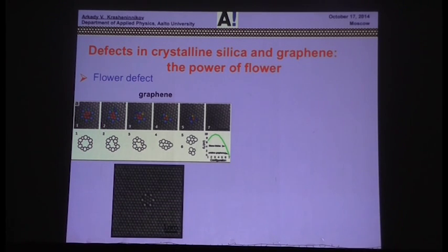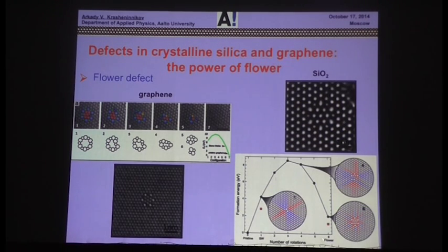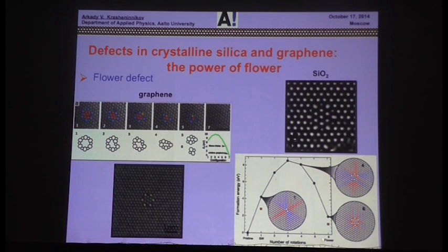Versus the beautiful flower defect in graphene, essentially you rotate 6 bonds, one after another. The process can go either way, from pristine graphene to flower defect, or from flower defect to pristine graphene. All the atoms are there, you do not lose atoms. This is an example of a flower defect in graphene, and the same works in SiO2. Actually, it's rotated by 90 degrees. If you rotate by 90 degrees, it's pretty much the same structure as you see here, but the scale is different. The formation energy of this defect is much lower in SiO2 because strain fields are compensated very efficiently for this defect.